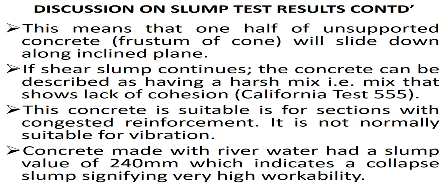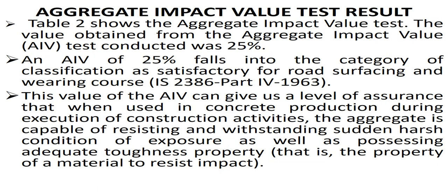Concrete made with river water had a slump value of 240 mm, which indicates a collapsed slump, signifying very high workability. Aggregate impact value results.